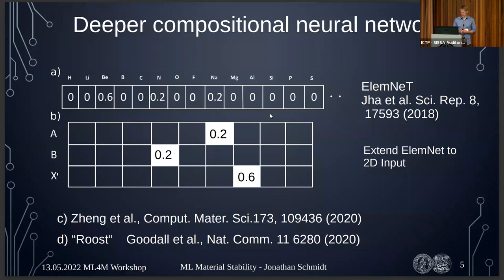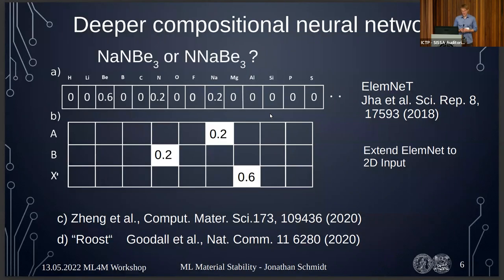That worked for single prototypes. Over the last years, people tried deeper neural networks based on composition, but there's a problem: if we consider a perovskite structure with multiple atoms, we don't actually know which atom occupies which position in the structure, so we can't learn to differentiate polymorphs properly. Purely compositional models don't work well, even though some show good performance on the Materials Project dataset.